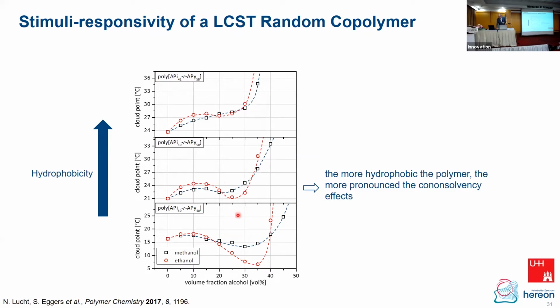And what you see here is the hydrophobicity of the copolymer is increasing from the bottom to the top. This is just because the PAP component, so the more hydrophobic one in the copolymer, is increased. So in the top, you have the highest amount of the 6-membered ring, and in the lowest, you have the highest amount of the 5-membered ring, which is better soluble. So these effects are nicely following this idea of what I just